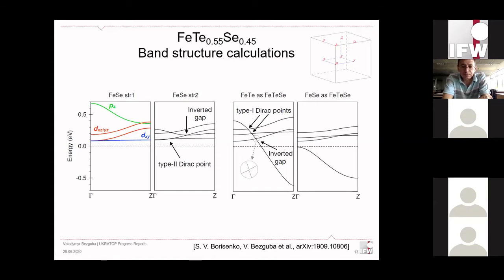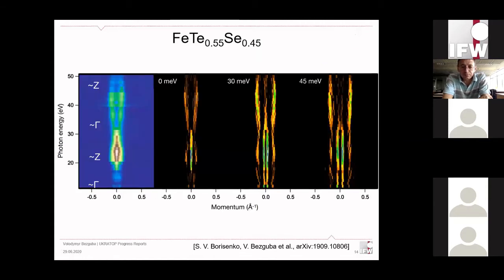So we performed a lot of experiments. A lot of data was accumulated, and a summary of it is this kz map. It's a kz map because, important to notice, the excitation energy of photons in the case of ARPES corresponds to kz. So a nice feature of synchrotron is that we can measure with different photon energies, thus we can map the kz. So here we can see several Brillouin zones, and the first most visible thing here is that there is no visible band which would be in the center at any kz.